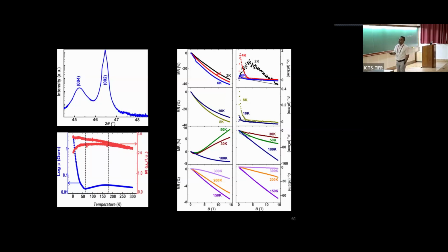When we look into the magnetization data as a function of temperature, there is a cusp-like structure which signifies an antiferromagnetic transition, and then there is another ferromagnetic-like structure which we don't know yet. We got these results just last month or so, and these two correspond very well with your resistivity data. Then we look into the magnetoresistance data. At low temperature, it has a negative magnetoresistance of around 40%. But as we increase the temperature around 30 Kelvin, there is a transformation from negative to positive magnetoresistance.